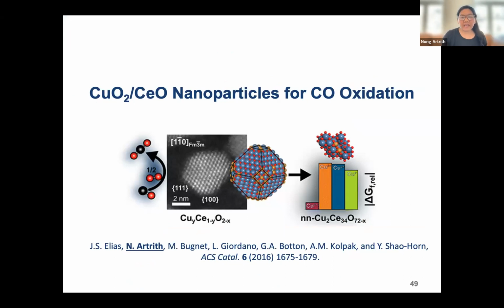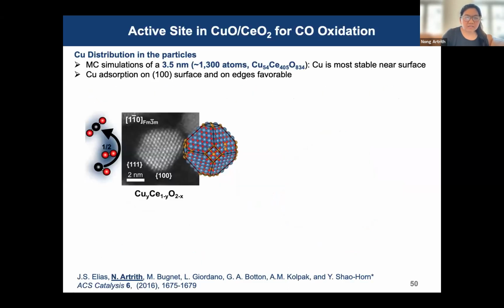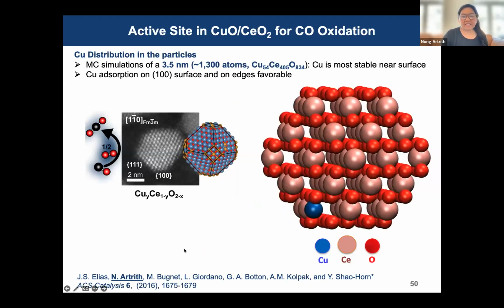How can we help experimental collaborators to find where copper sits in these structures? Joseph Elias just came to me and said, I can see that you can find the copper gold structure rearranged in your nanoparticles. Here I have copper cerium oxides, but I don't know where my copper sits in these structures. Could you please help? I said, okay, maybe we can construct the same kind of machine learning models, but use a different type of database. So we construct the machine learning models with copper cerium oxides, and then we use again the same methods, Monte Carlo and simulated annealing.